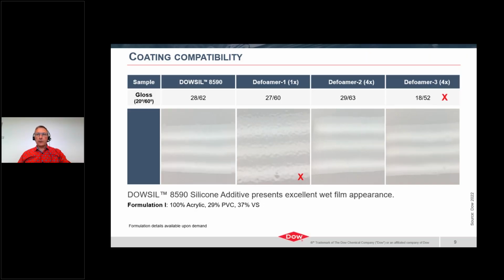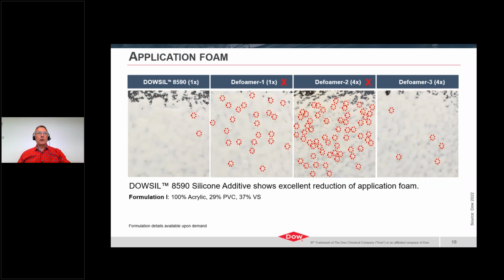And finally, for the 4th option with the mineral oil, although the appearance is good, we're observing what is typically observed with mineral oil-based defoamer, which is a lowering in the gloss level in the final film. When comparing the same formulations, but this time applied by roller application on a test substrate, we can see clear difference in the defoaming performance between the 4 materials.